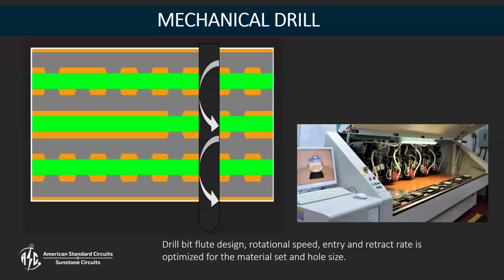You can see in this representation of a drill bit going through the panel that we're drilling 25% further than the actual bottom of the panel. This is done into a phenolic material or another harder material on purpose to get a good, solid, smooth drilled hole. I'm sure most people have seen drilling a hole into a 2x4, and if you don't have anything behind that 2x4, when you exit, it tends to splinter and volcano out that hole on the backside. Same is true with circuit boards.